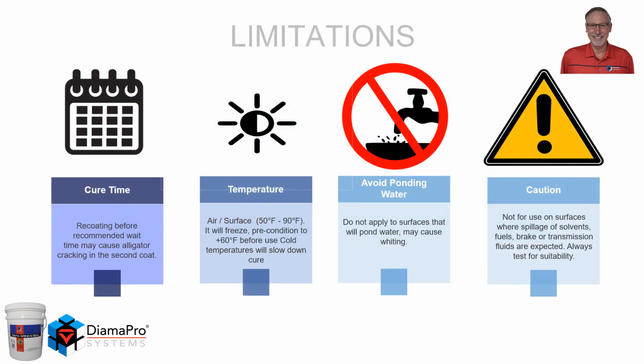All materials have limitations. Let's look at the cure time. If you apply your second coat before the first coat has had a chance to release all the water and solvent, you could cause alligator cracking in the second coat or retain some of that white appearance that we saw during the application. Temperatures, air and surface temperature during application needs to be between 50 and 90 degrees.